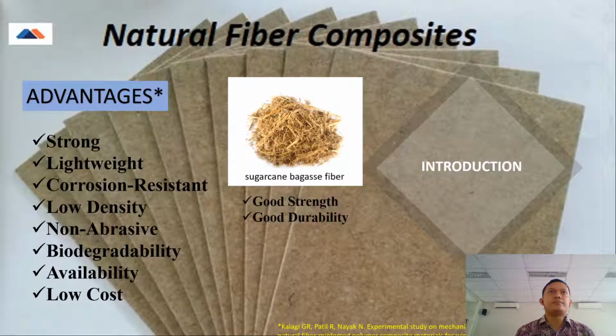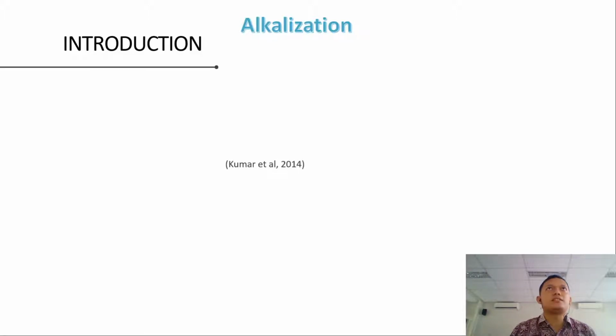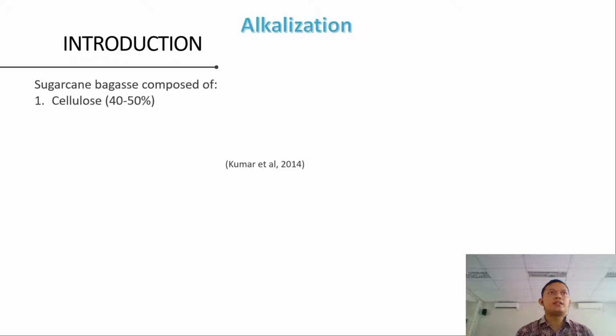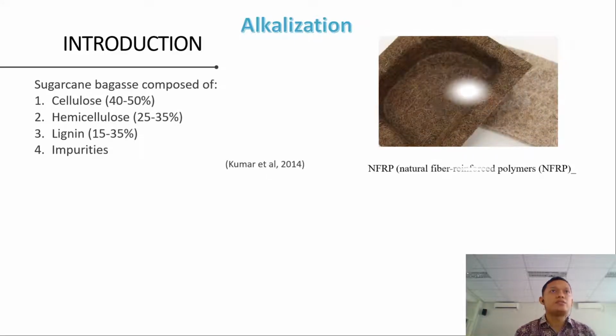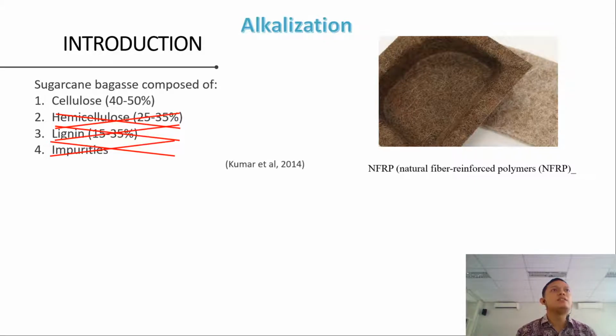Now let's talk about alkalization. Natural fiber composite needs a treatment called alkalization. NFC, such as sugarcane bagasse, is a complex composite composed of cellulose around 40 to 50%, hemicellulose around 25 to 35%, and also lignin 15 to 35%. According to the reference Kumar et al. 2014, sugarcane bagasse is composed of this, but we need to remove the three: hemicellulose, lignin, and impurities.